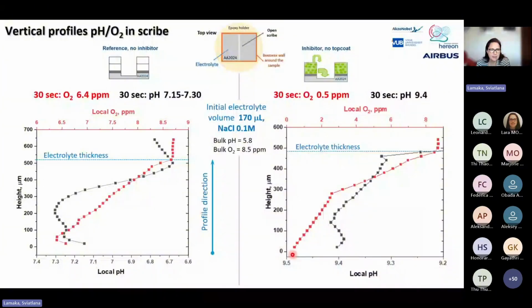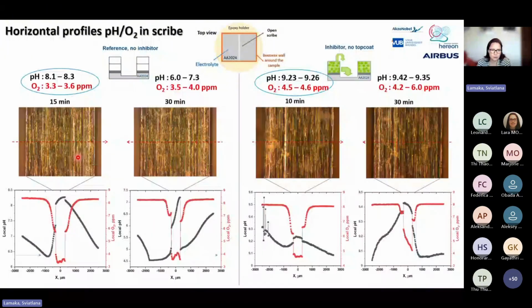And this is because there is already a protective layer of aluminum lithium LDH that builds up in the scribe and prevents diffusion of oxygen to the aluminum surface, where then reduction takes place. Then we also performed a mapping for the reference sample, oxygen and pH, and for the inhibited sample, oxygen and